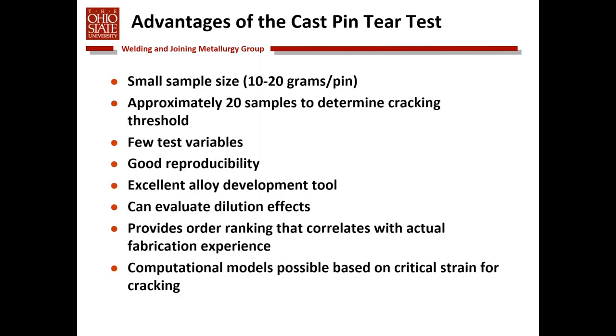So the advantages, as I see them, is we've got a small sample size, you don't need a lot of material. You can develop one of these curves with about 20 samples, maybe less. There are very few test variables. Reproducibility tends to be pretty good. It's a great alloy development tool because you don't need much material.